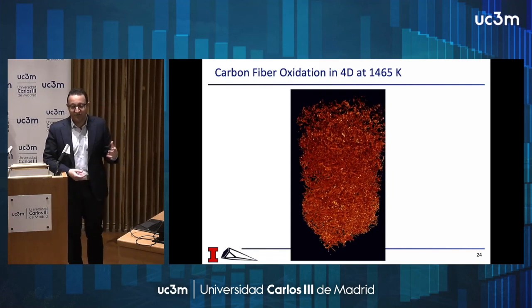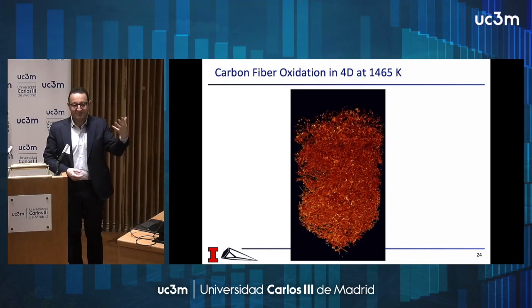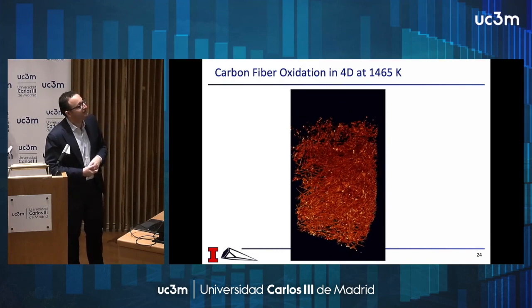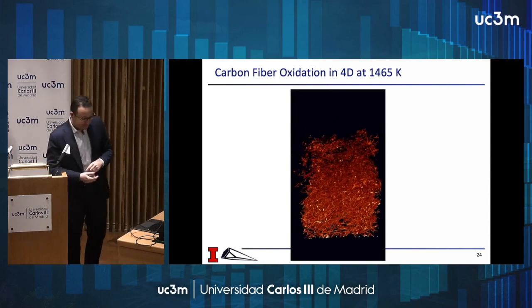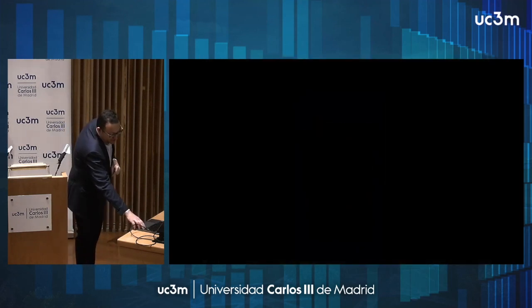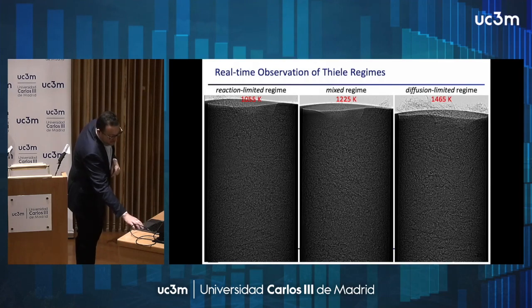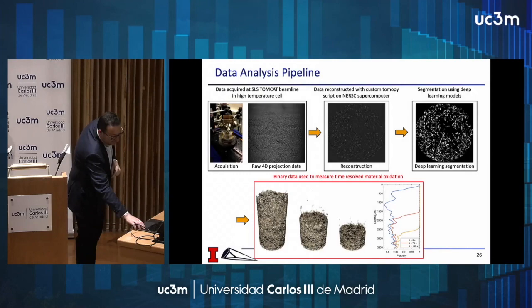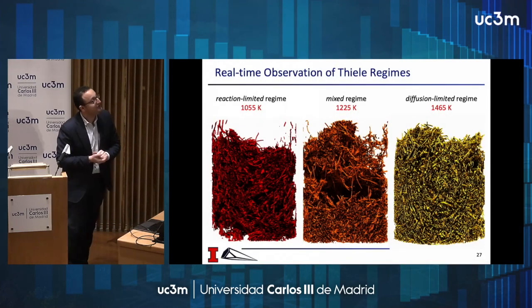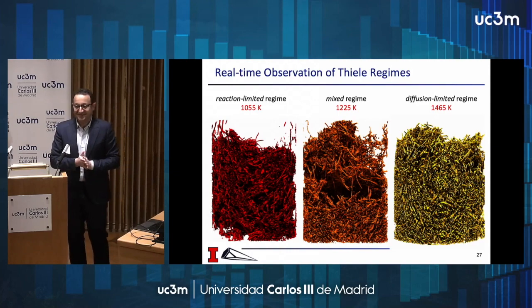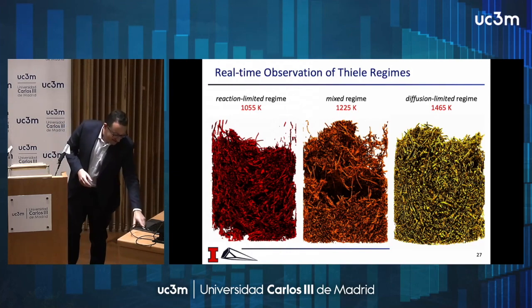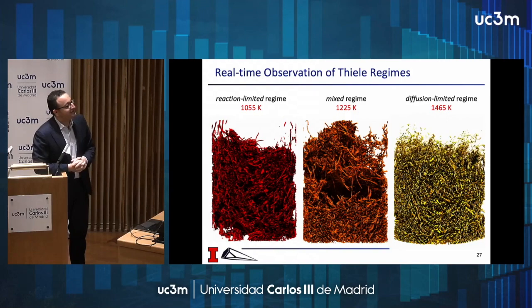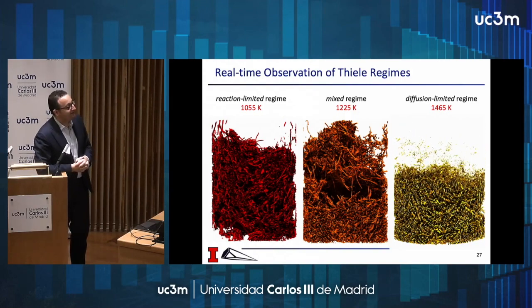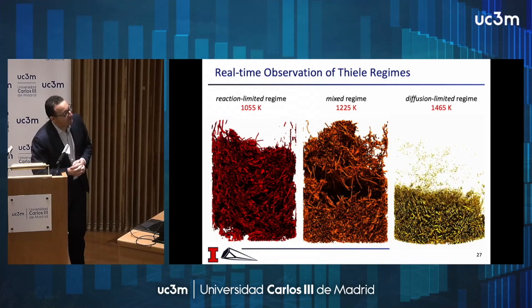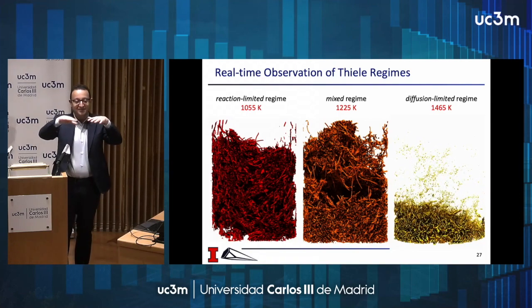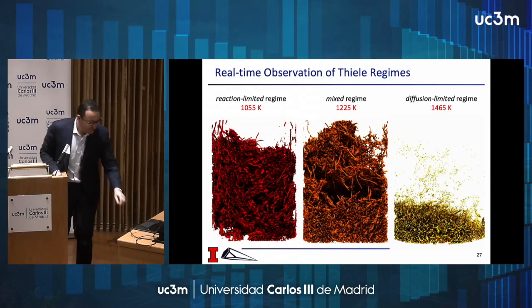So we can fully resolve in 4D how the material decomposes under the effect of oxygen. So remember, I showed you the three regimes. Actually, I'm going to skip this and go directly to the result. I'll show you the three regimes that we can capture numerically. So now with these techniques, you can see these in fact experimentally, and so we can resolve the diffusion limited regime, where you see that the carbon is all gasified at the surface.